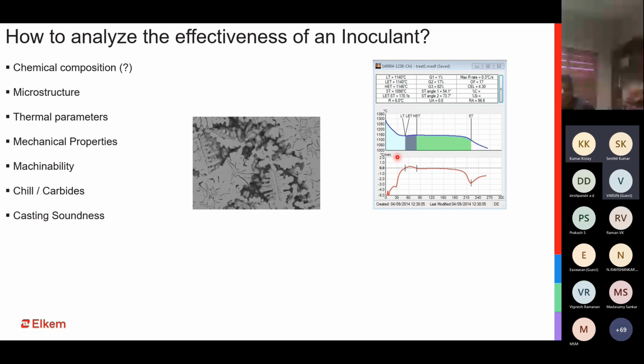You look at the recalescence. So these parameters give you a very direct indication of the effect of nucleation. Further, if you're able to achieve a good microstructure, if you're able to achieve a good thermal parameter, definitely the mechanical properties are the next things which will give you an indication that your metal has been properly inoculated.